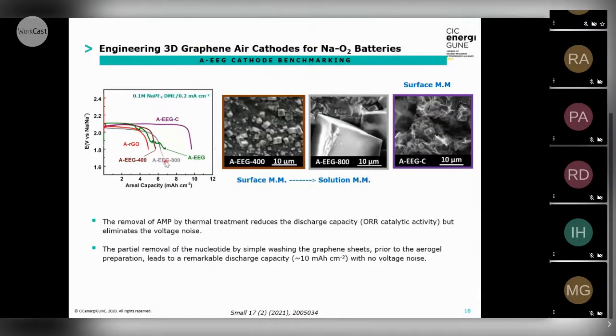So what we did is we followed two approaches. First was to heat treat this sample, in order to remove maybe many functional groups on the surface and see if we could improve this performance, or basically to clean, to wash this material. Maybe the AMP content was too high, which prevented the oxygen diffusion and the oxygen reduction or evolution reactions. So in this case, what we saw is that this clean EEG has a really high discharge capacity. And we can see also that there is a different mechanism.